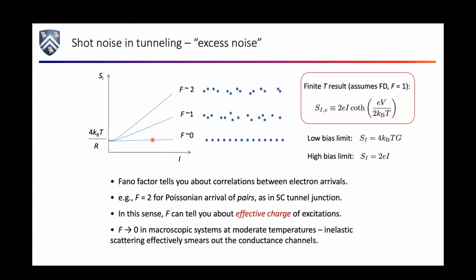If my electrons were always paired, so I had Poissonian arrival of pairs, I would get a Fano factor of 2. If my electrons came perfectly evenly spaced in time for some reason, you can make Coulomb blockade systems where the repulsion is very important, and you would get a Fano factor of 0, right? Because if the electrons truly came like clockwork, there's no fluctuations in the current. And also, if the electrons were a perfectly continuous fluid, imagine that there's no such thing as quantization of charge, then I would also get a Fano factor of 0, right? If my charge wasn't lumpy, I wouldn't see any fluctuations in the current. The average current would tell me the whole story.